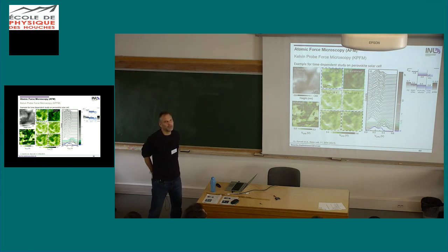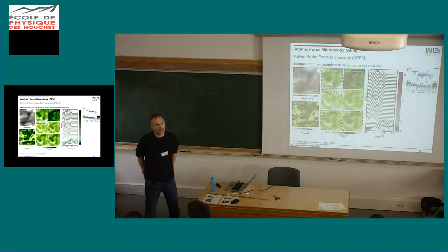I mean, we heard yesterday from Laurent about the quasi-Fermi-level splitting. But of course, if you make a device with an open circuit voltage, you also get all the trouble with the contacts, right? So your open circuit voltage normally doesn't match that one. So in this sense, if you just measure on the absorber, as is claimed sometimes, you cannot measure the open circuit voltage because you don't have the contact there. Or you have a contact which is your tip, which again is different from a device. So it's not as straightforward for sure.